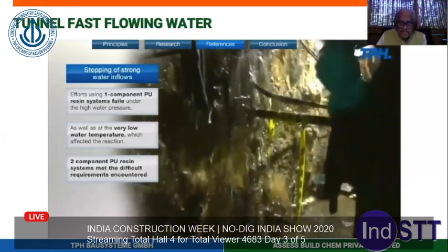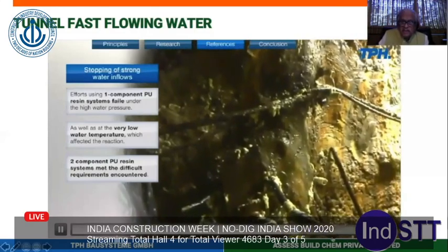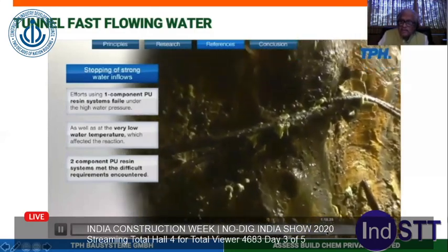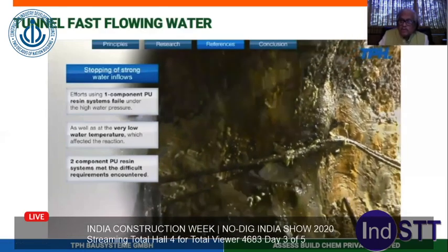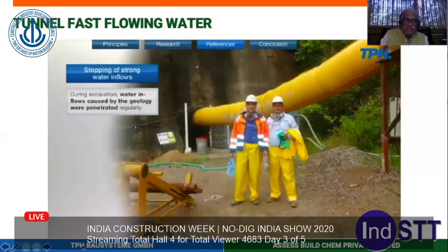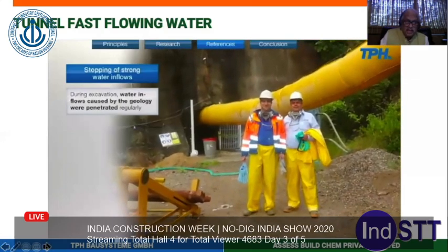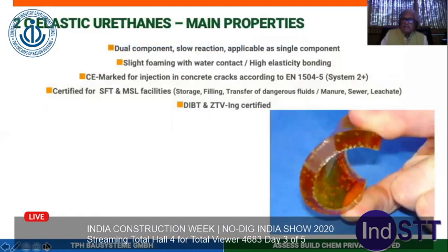The foaming capacity is less. Maybe the foaming capacity is up to 14 or 15. So they can really stop this water when you use proper machinery to push this material inside. So this is how you go from a one component material to a two component material. Then there are flexible materials, ductile filling materials. When you are talking in terms of pushing these materials into cracks in concrete, in podiums, and in other structures where flexibility is required, polyurethanes are very, very, very flexible.